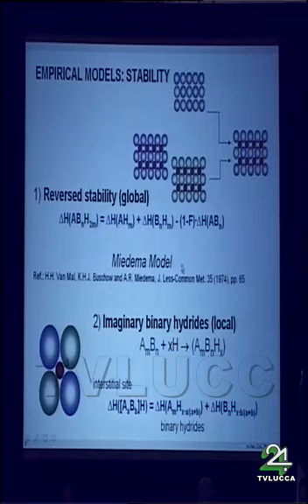Now, that was the amount of hydrogen in our system. The second important parameter, of course, is the stability. And here again, we have empirical models. The first one is the Miedema model, the model of reverse stability, which simply means the more stable an alloy is, the less stable is the hydride, and the other way around. That is based on the assumption that when hydrogen enters the lattice, it has to partially break the bonds between the metal atoms. That's why we have this factor 1 minus F here, and that is the disadvantage of this model. There is no ab initio way to calculate this parameter F, so it describes systems which are similar or known from experiments, but it doesn't allow us to directly calculate the stability of a certain intermetallic compound.